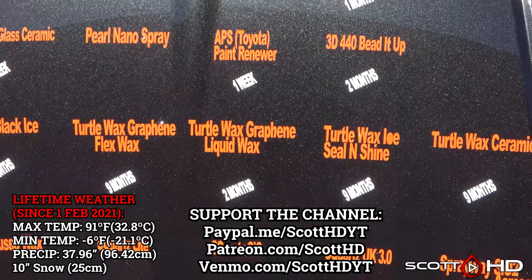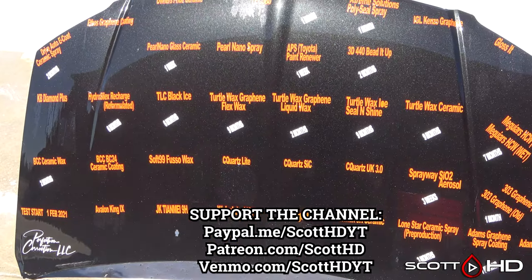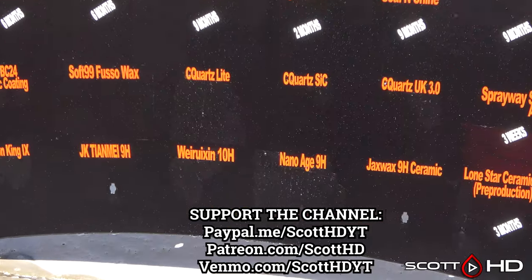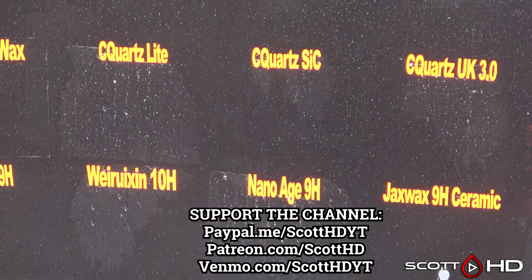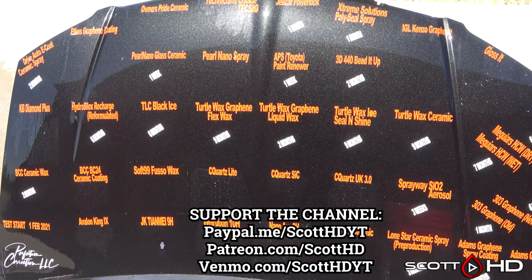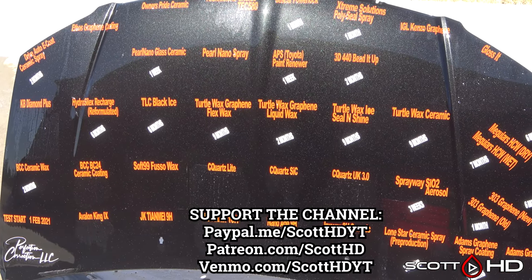So normally here, I'm going to do my usual wash, but I generally never make exceptions to how I wash and what I wash with, because I don't want to introduce any other outside variables. That being said, this particular test has something weird going on with it. I think it was the 10 inches or 25 centimeters of snow that we had right after this test started early last year, along with -6 Fahrenheit or -21 Celsius temperatures at the same time for about a week. And that appears to somehow have weakened the hydrophobics on this hood.